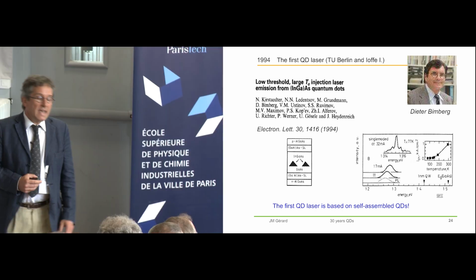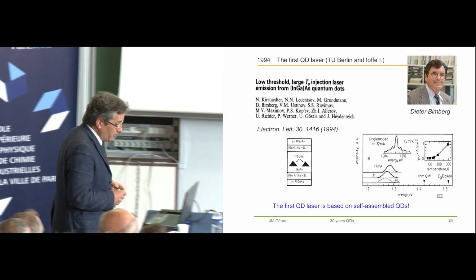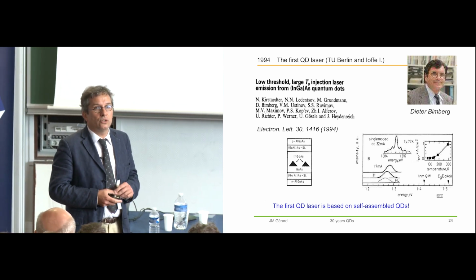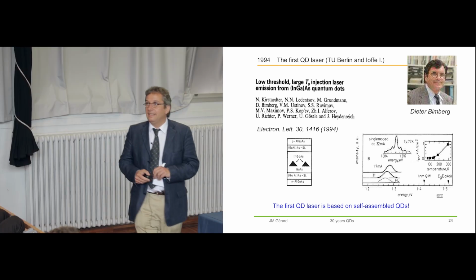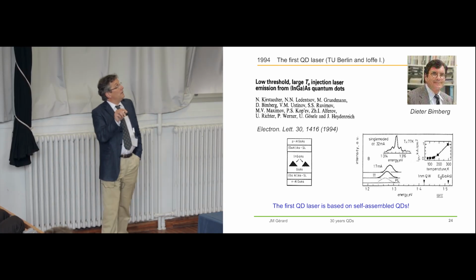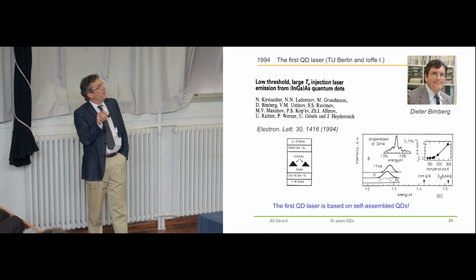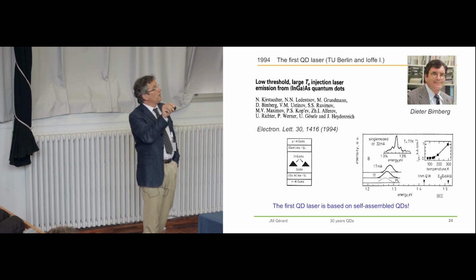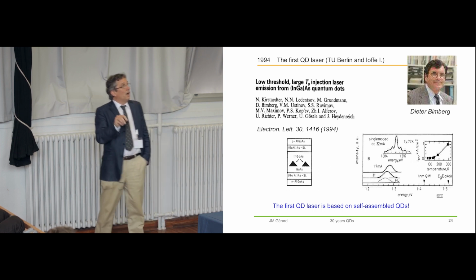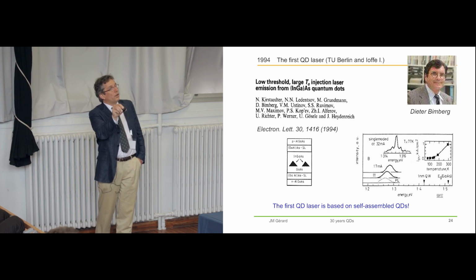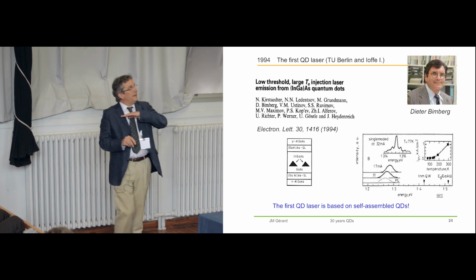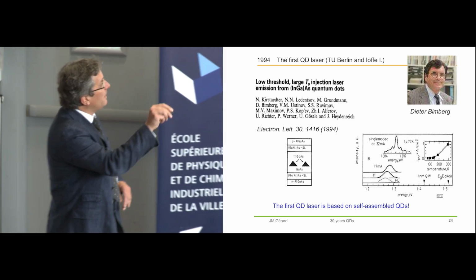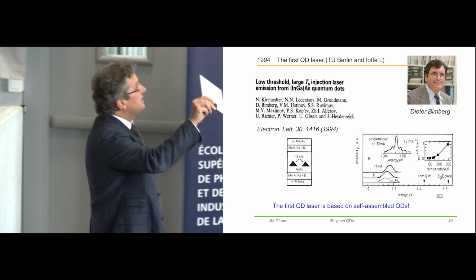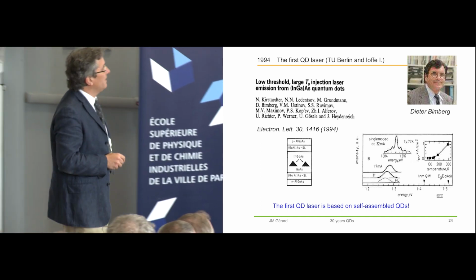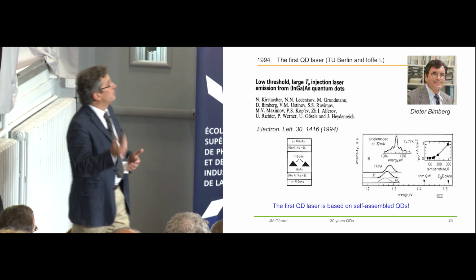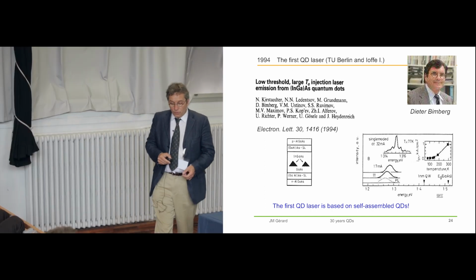And the third main event occurring at that time was also the first demonstration of a quantum dot laser by the group of Dieter Bimberg. Dieter Bimberg, in collaboration with the Ioffe Institute, grew a sample for which quantum dots were placed in a PN junction. And they could show that at low temperature, 100 K here, the laser displayed a very low threshold and a temperature insensitive behavior. It degraded somewhat when they went to room temperature, but in the next months, the properties of their lasers improved a lot.